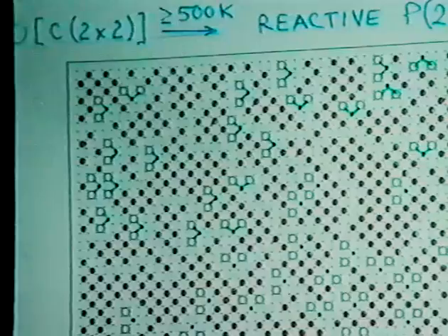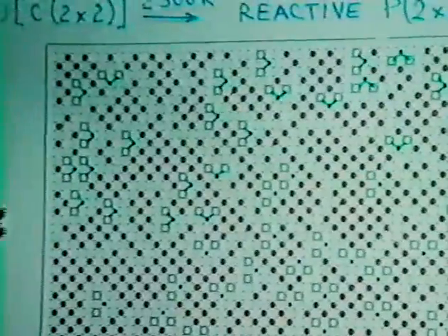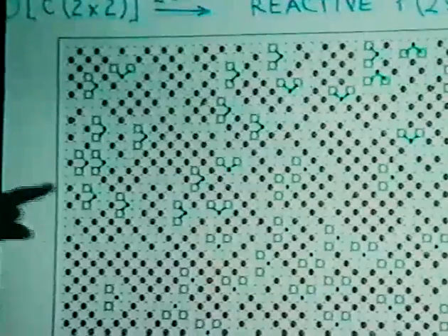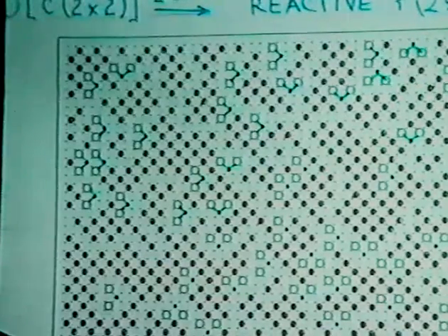they remain there. Now if we have a small concentration of dichloromethane such as here, then we can put onto the surface a lot of oxygen, the red spot. So oxygen makes its own regular structure, and there's some dichloromethane.